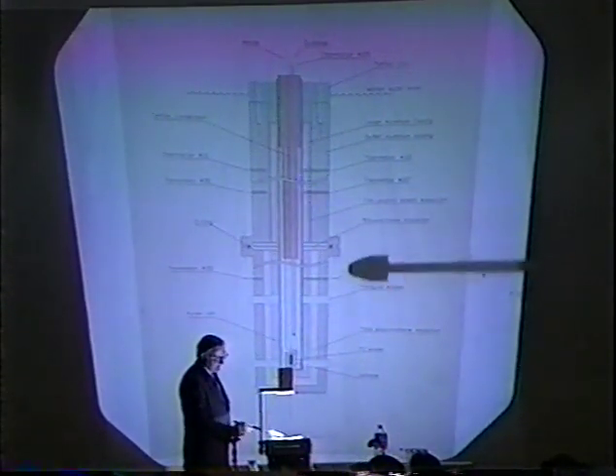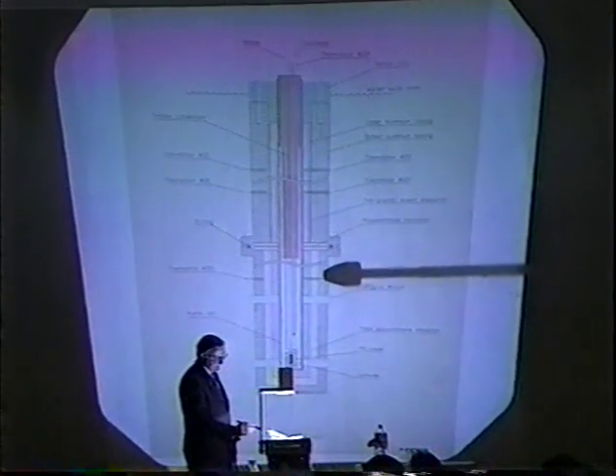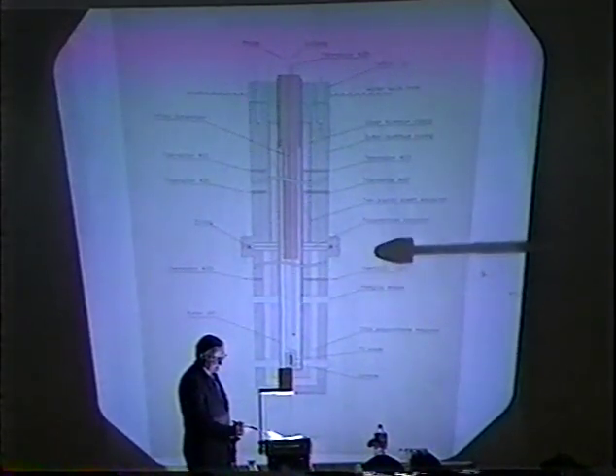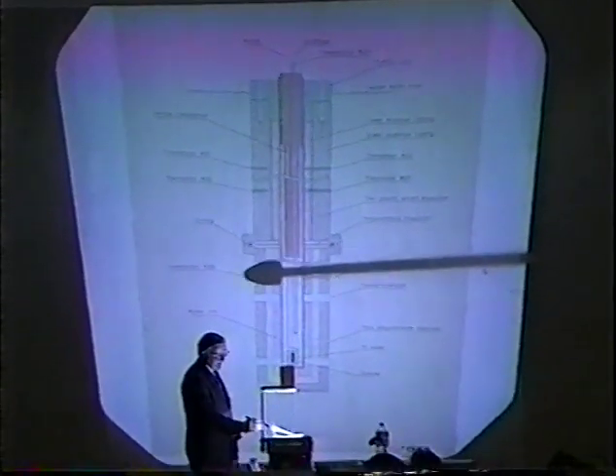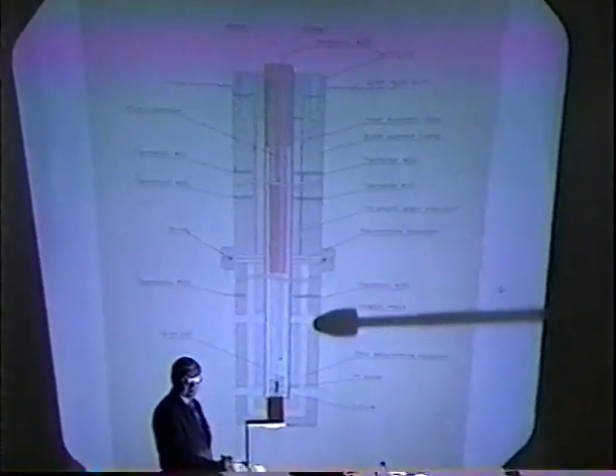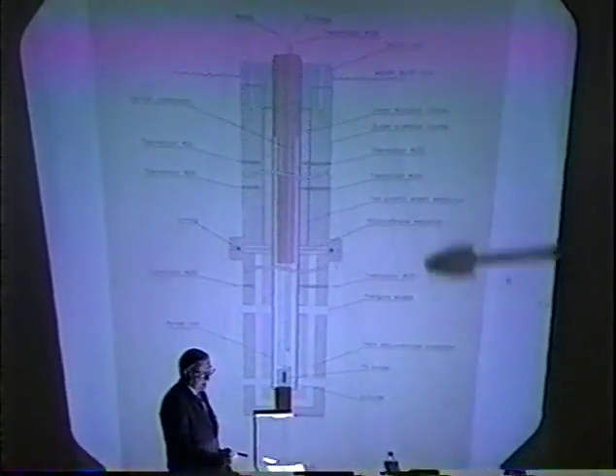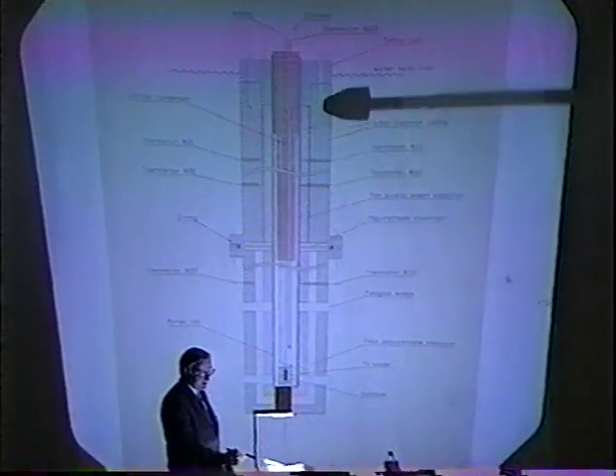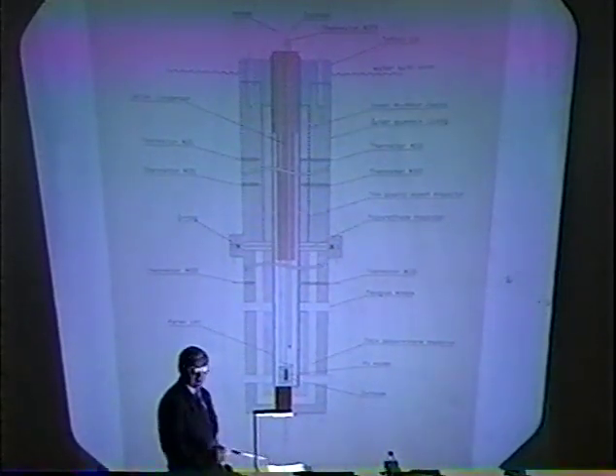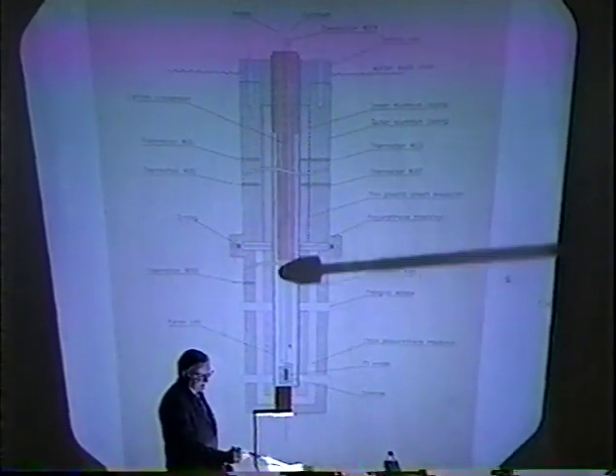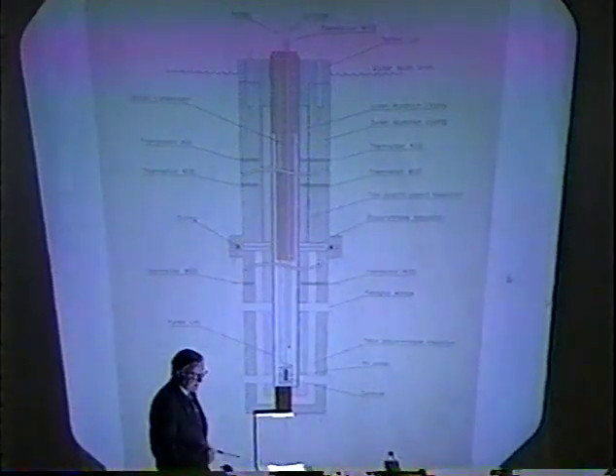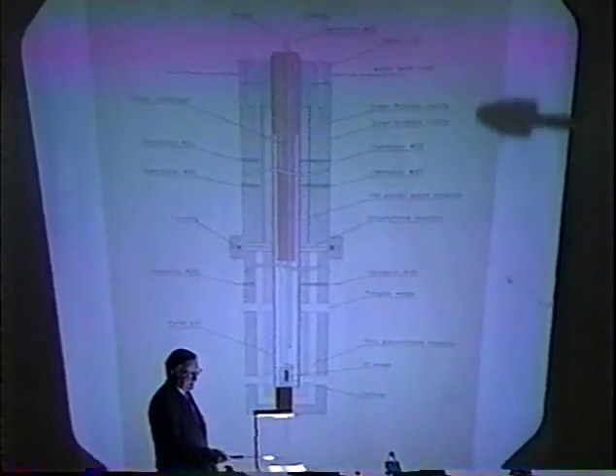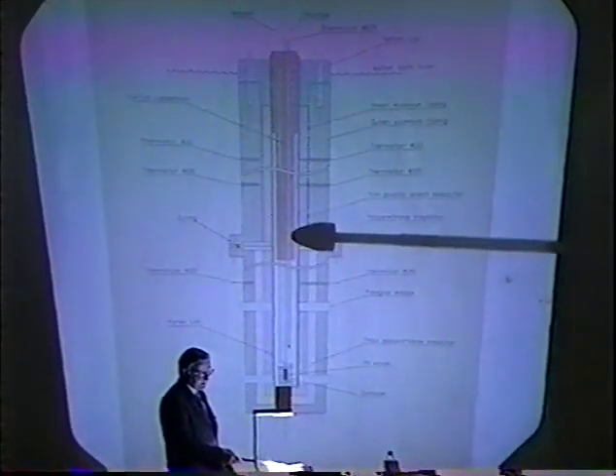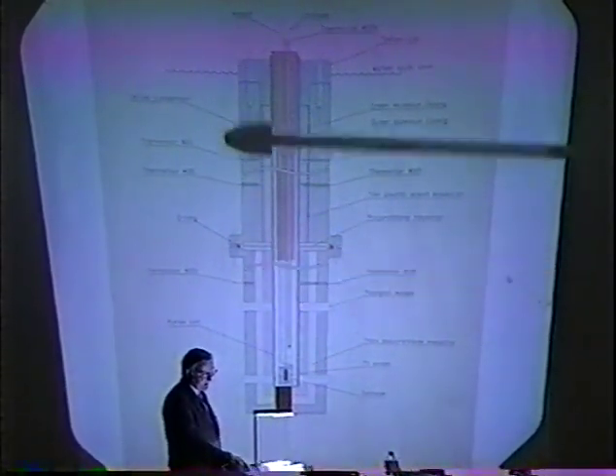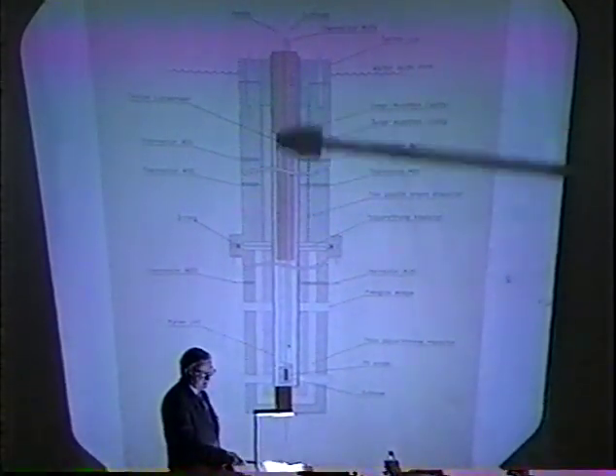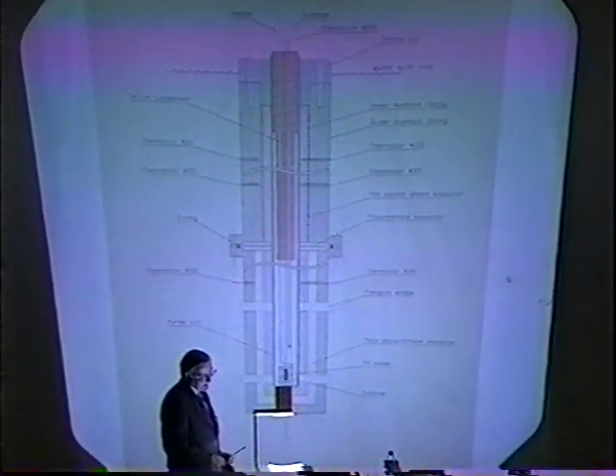So we put thermistors in the cell. We also place thermistors in the inner jacket and the outer jacket, so we can measure directly a temperature difference between the outside and the inside of the cell. And we can do the same thing in the upper half, the measurement or condensing section, at various vertical positions. In the center of the calorimeter, we can put a condensing plug. This can also be considered a device for controlling the amount of condensation or the linear heat rise in the calorimeter. As I will show in a few minutes, this has been modified as well.